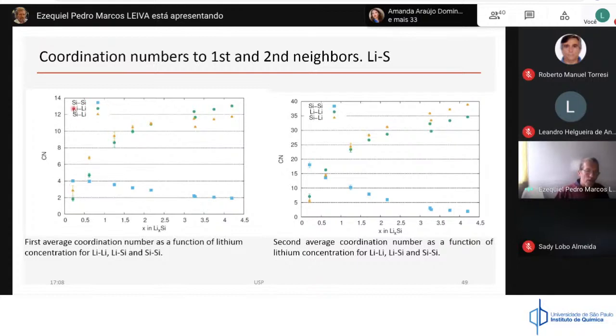When you look into the silicon neighbors of silicon, you will see that you start with 4 neighbors, which is expected for the tetrahedral geometry of silicon. But if you put more and more lithium, you will see that your number of neighbors of silicon decreases, and comes close to 2. This is correlated with the formation of chains that we have seen before. This is evidence for the formation of chains. Even if you don't look at the movie, you can notice that you have a number of neighbors close to 2. You can look also at the second number of neighbors, and you can see here that it increases from, let's say, 5 to about 35, or of the order of 40.